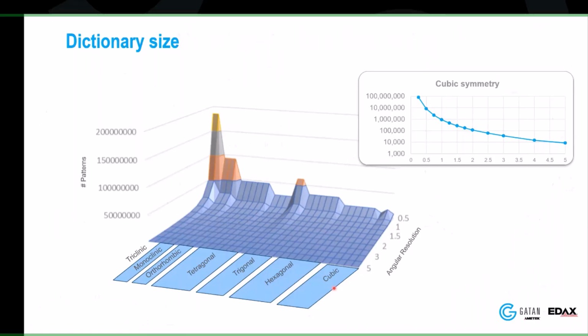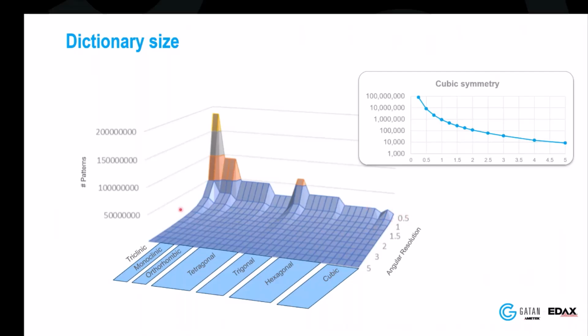And this is where the geological side starts to become a problem. On the geological side, we're usually dealing with things that tend to be lower symmetry, which is over here on the left. Over here on the right-hand side, looking at cubic space to get relatively high angular resolution, I'm in the, let's say, 15, 20 million patterns. As I go to lower symmetry materials, we can see this really starts to ramp up quite fast, and with triclinic spacing you can start to see how many patterns you're looking at.